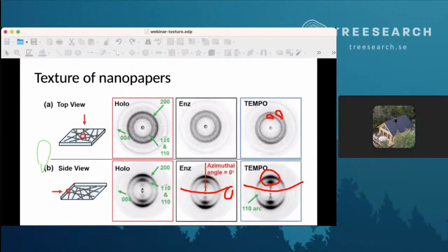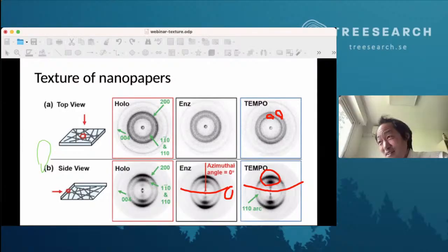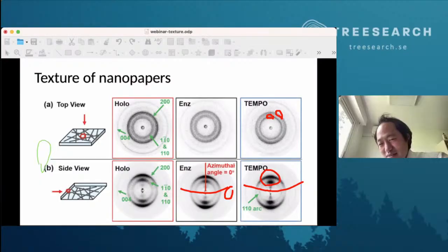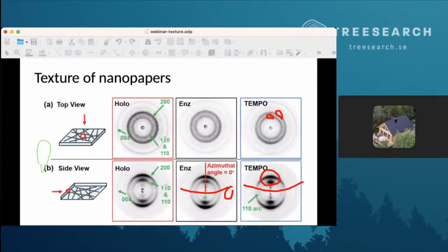No, that I can buy. But I was more... you've been looking into this. If you had some reliable references, I would have really enjoyed them. No, but my preference is to have some experimental parallel. So it would be nice to have a way to achieve this. Yes. So far, nobody. For instance, we have another thing that would be interesting and links to what Per was saying also: if you heat cellulose at 130 degrees for a while, you will change the contact angle from around 40 to 90. Yes. And nobody knows why that is.